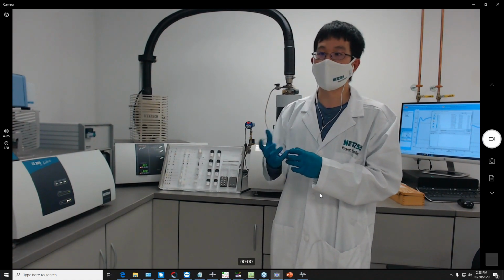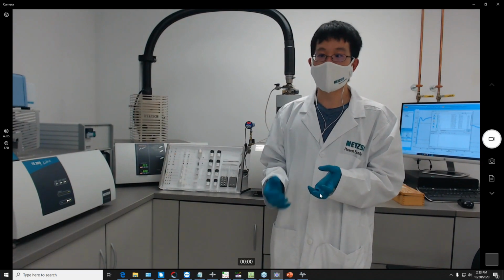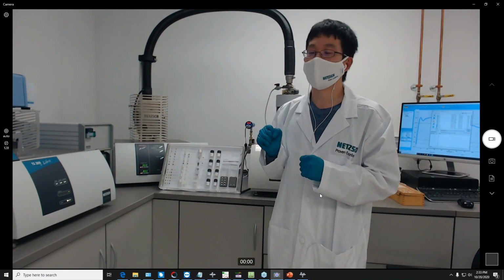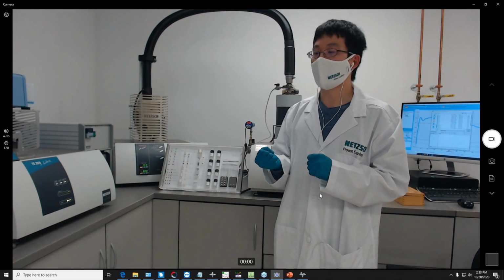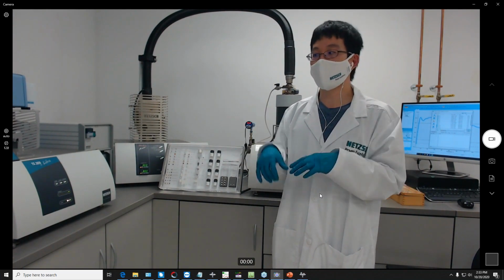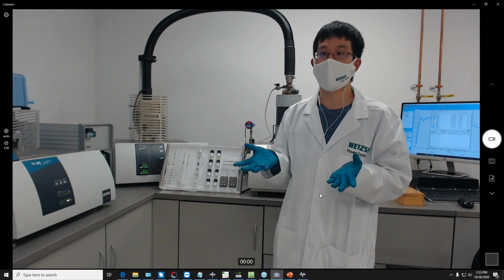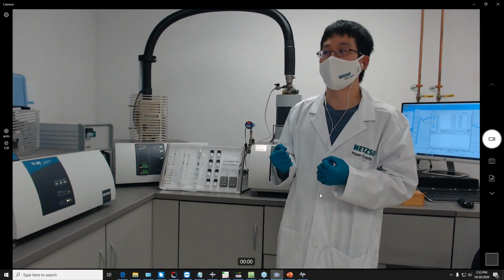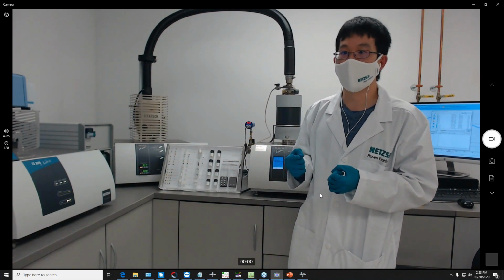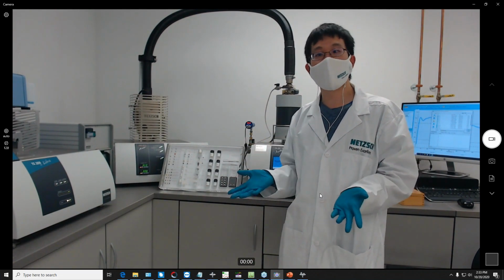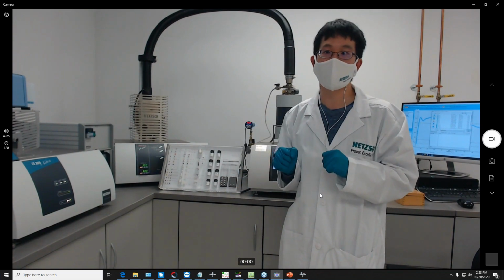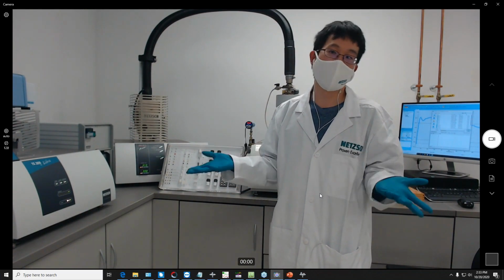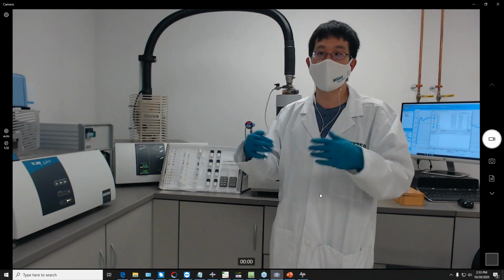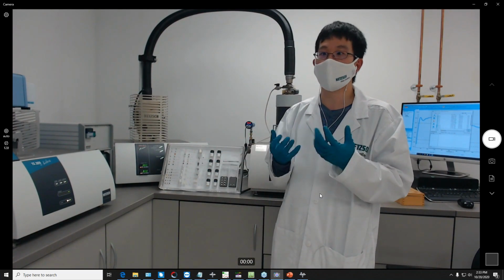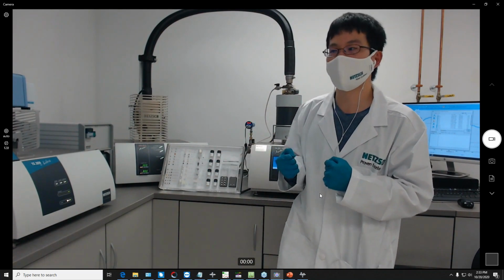So it allows the gases of your sample to come out of the crucible, as well as any interactions with the purge gases that you're running to interact with your sample. Let's say you run in an oxygen environment, you could have oxygen react with your sample. If you're using a reducing atmosphere like H2 argon, you could have those reducing atmospheres interact with the sample.